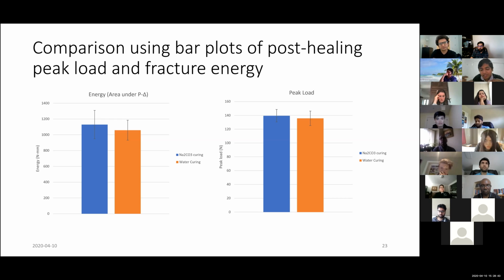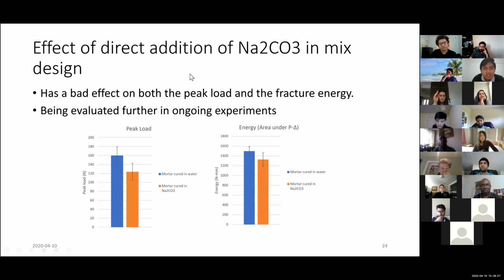So if we introduce a slip damage in a fiber, the sodium carbonate is not really able to help. It's performing slightly better than water, but in terms of statistical difference, there is no real statistical difference. Then I tried, in this case, directly adding sodium carbonate into the mix instead of curing it. If I directly add sodium carbonate into the mix, I observe a bad effect on both the peak load as well as the fracture energy.